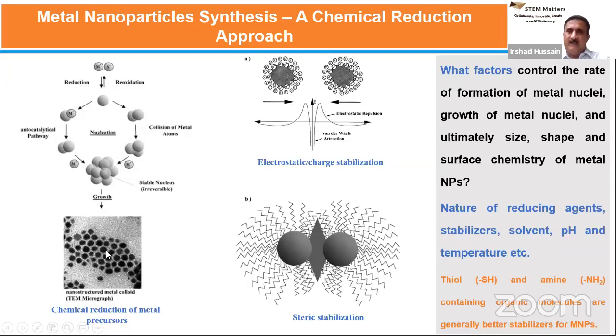And for this purpose, we normally use two different approaches to stabilize these nanoparticles. One way to stabilize these particles is to coat them with charged molecules which have either positive charge or negative charge. And once those molecules are at the surface of nanoparticles, all these particles will have similar charge. For example, they will have negative charge in the case of sodium citrate. And due to similar charge, these particles will repel each other due to electrostatic repulsion, and they will stay away from each other, and they will not agglomerate.